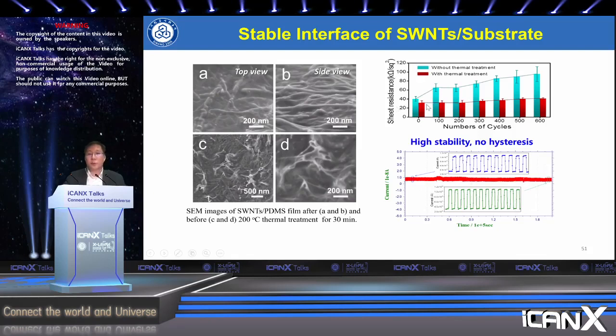And also, when we treat this interface at about 200 degrees C, at these temperatures, the volatile silicone molecules in the form of short PDMS chains will form a conformal layer of about 2 to 3 nanometers, and subsequently cross-link to result in the formation of a silicone coating to get a very stable interface.